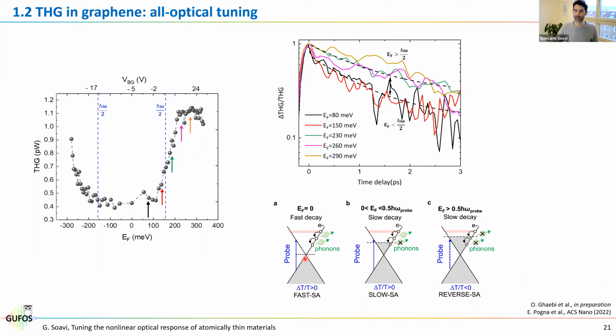When the graphene is at the Dirac point, so we have a low doping, then you pump electrons up in energy, and there is a lot of space in the reciprocal space for electrons to scatter with the optical phonons. And this electron-phonon scattering is the initial process for recombination of hot electrons. However, as you start increasing the doping, you sort of fill the phase space until at some point you completely quench this scattering between hot electrons and optical phonons. And this is indeed what we observe also here.